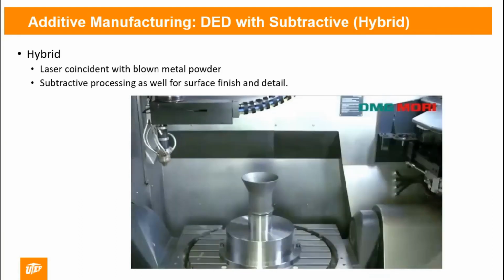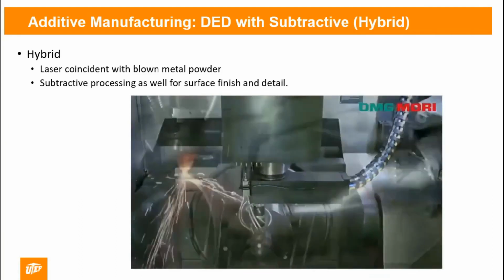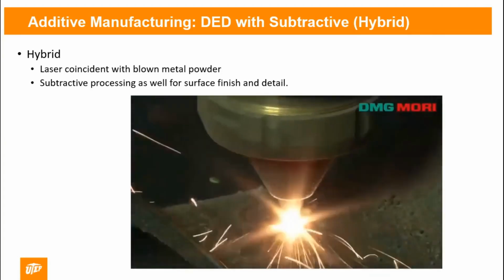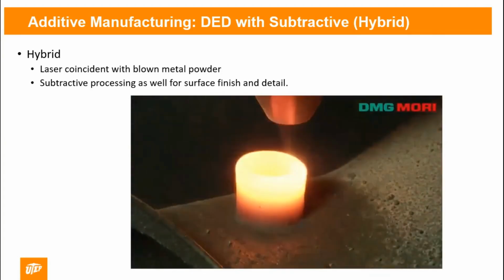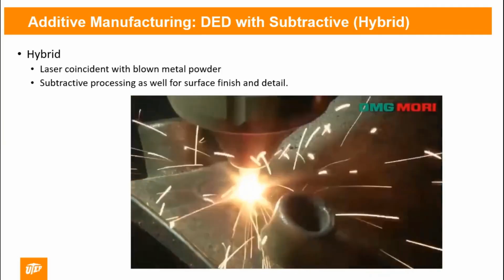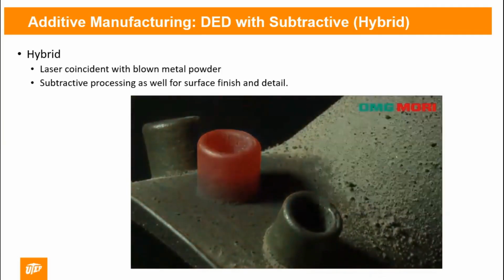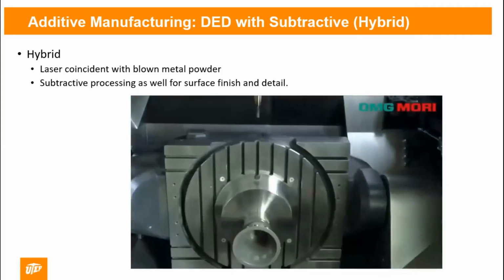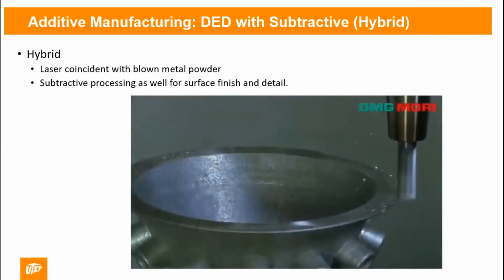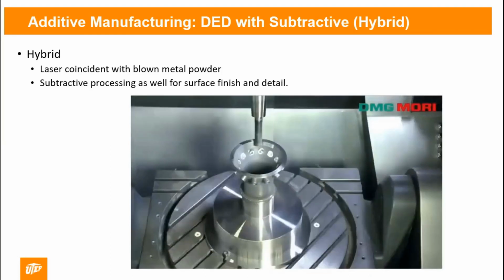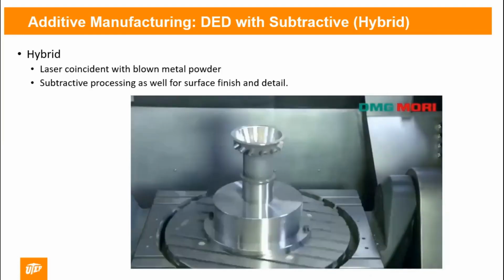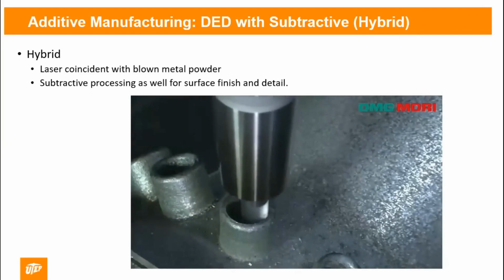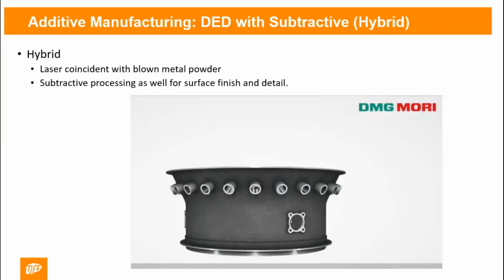And I've actually worked with the University of Bremen in Germany to insert electronics into this technology. And at Oak Ridge, we used a similar system, not this one, but very similar. And we just embedded a ceramic 3D printed object. It was nothing special, it was just a chunk of ceramic we had printed. But the idea is if we can make that ceramic large enough, and if we can embed electronics in the ceramic, then we can embed the ceramic into the metal. And I'll show you an example of that. So we're working on that. So those are the 7 forms of 3D printing.